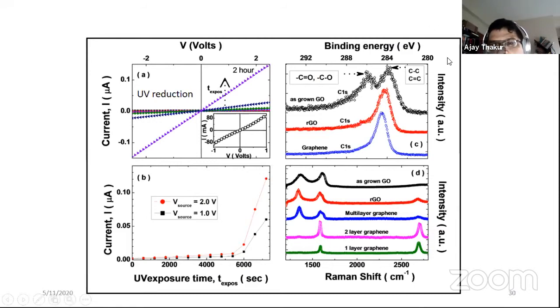On the top right panel, we are showing X-ray photoemission spectroscopy data, and this is primarily to compare how our reduced graphene oxide compares with graphene. And you can see the comparison of the red curve with the blue curve, and this black curve corresponded to the parent graphene oxide sample which was made.